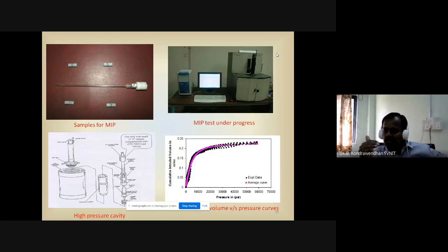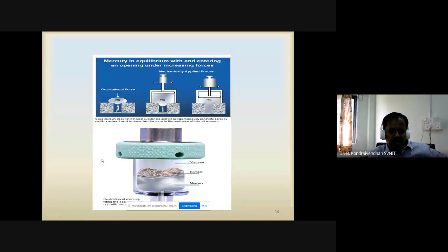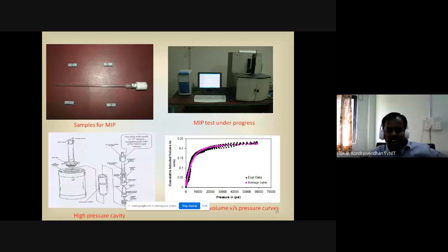Once the low pressure is over, then we have to switch to the high pressure station. The high pressure cavity should be like this. Here we are using hydraulic oil. There we have to apply pressure up to 60,000 psi. At least we have to do 3 samples. We have to use 3 different samples for the same mix.